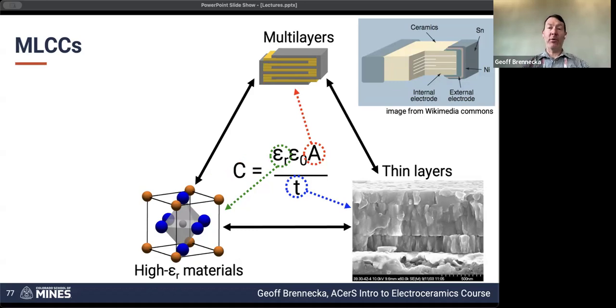So it doesn't actually have to break down and cause a lightning bolt within the material for a critical failure to be a problem. You could just have a little bit of extra roughness. If there's a nodule of the electrode that is pointing out, that means all of the field is going to be concentrated right there. It's going to be a leaky point. So you'll have a larger amount of leakage in that region. So often we do everything we can to minimize that surface roughness.